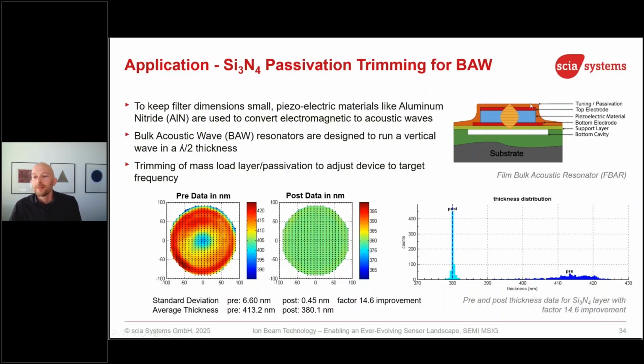100% sure. And such BAW filters are obviously very sensitive to mass change. I just explained it. You can detect picograms of mass change. And that's a challenge for the manufacturing of such sensors. You have piezoelectric material, electrode, and also on top some passivation layer. But in a typical sputter tool or PECVD tool, maybe you get 1% non-uniformity. And this 1% non-uniformity of thickness on a 200 millimeter wafer could easily yield a very low production yield. So in order to make such BAW wafers in volume production, you need well below maybe 0.1, 0.2% non-uniformity.